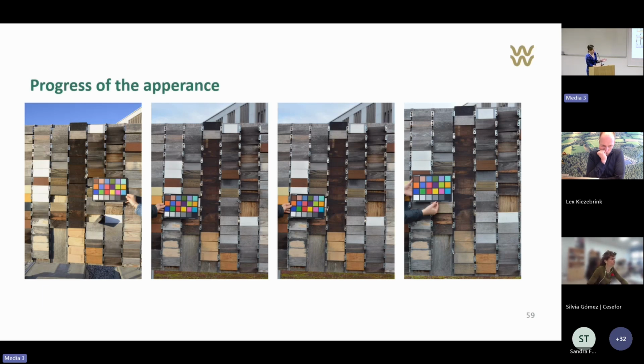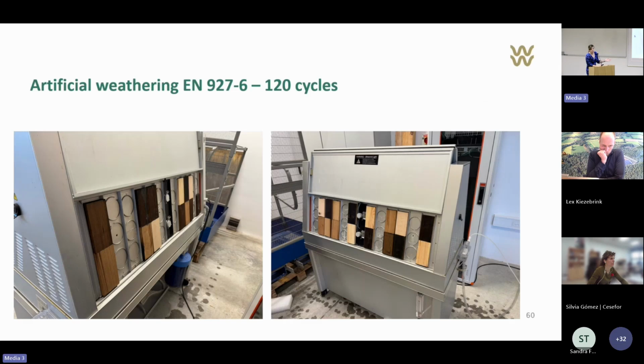Later we'll be able to see the change in appearance. Of course these weathering tests are long-lasting, and anyone dealing with materials knows this is typical for certain locations, so as a benchmark, artificial weathering is recommended. Here we used an artificial weathering machine, which doesn't fully simulate real service conditions because it just uses spray, watering the samples, and UV radiation. Nevertheless, this is the standard which allows us to compare the materials we were testing.